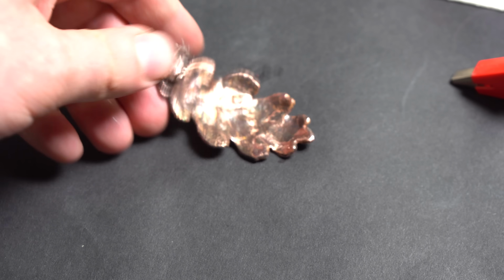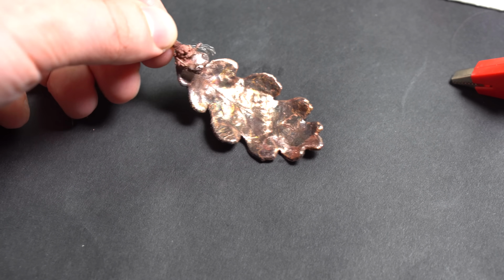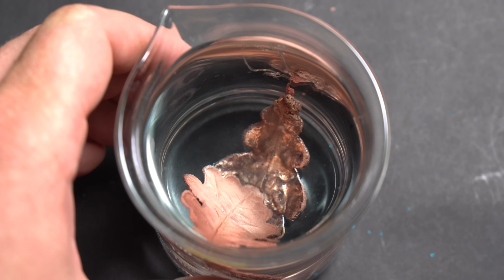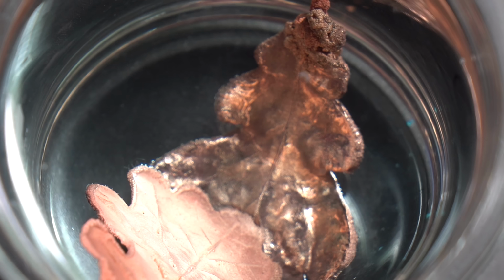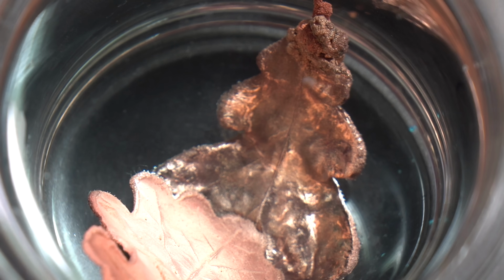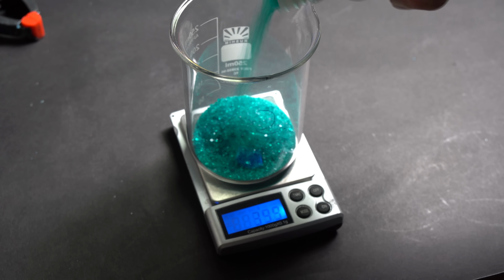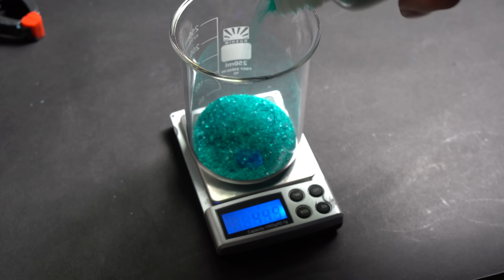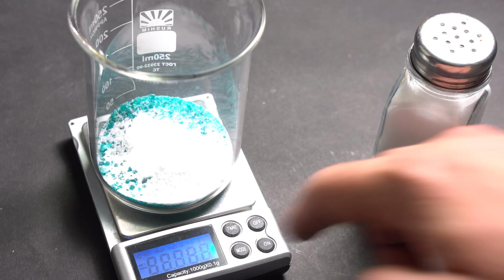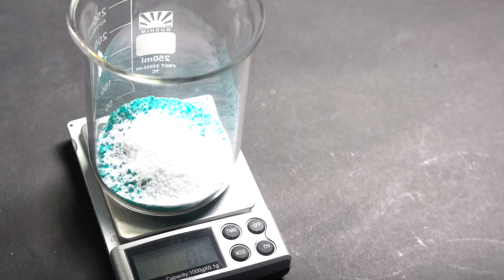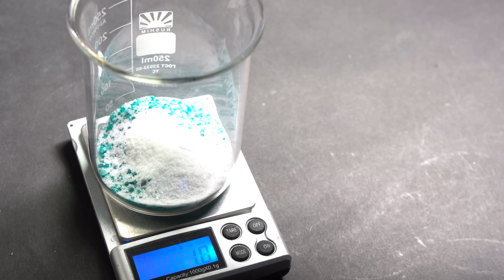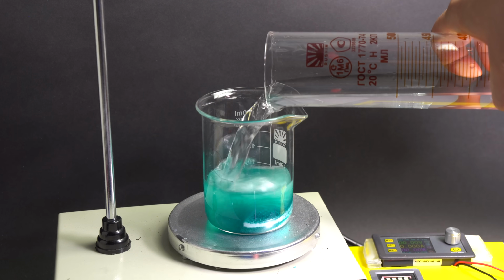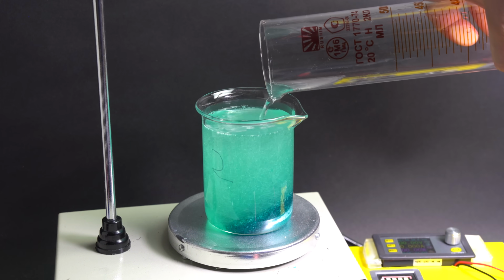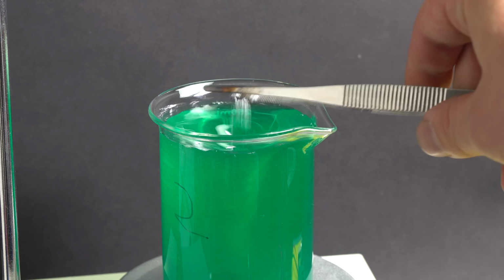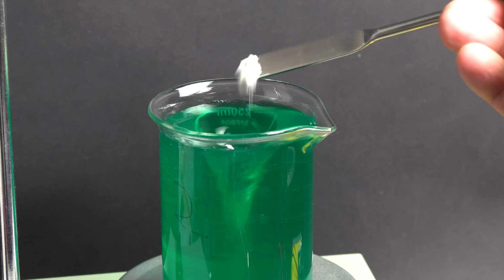To remove the copper oxide layer from the leaf and prepare it for nickel plating, I put it in a 20% sulfuric acid solution. While oxides were being removed from the copper-plated leaf, I decided to prepare electrolyte for shiny nickel plating from what I had available to me. I am pouring 50 grams of nickel sulfate, 5 grams of boric acid, and 2 grams of sodium chloride, which is regular table salt. After that, I am pouring about 250 milliliters of water and also brighteners. 1/100 of a gram of thiourea and 1/10 of a gram of disulfonaphthalene acid.